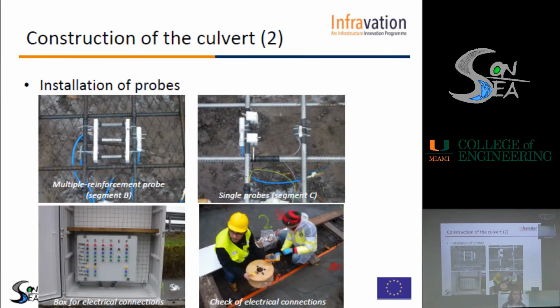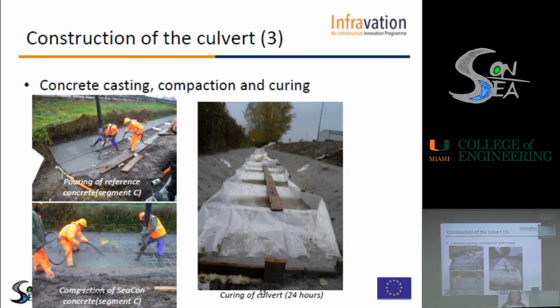All the connections were taken outside and connected inside this electrical box. And of course, before casting, we checked that all the connections were working properly, and they were, at least in the beginning. Then the concrete was cast in 3 different batches, and it was compacted through vibration and cured by covering the surface with a waterproof foil. It was a very rainy period, the time when this demo project was built.